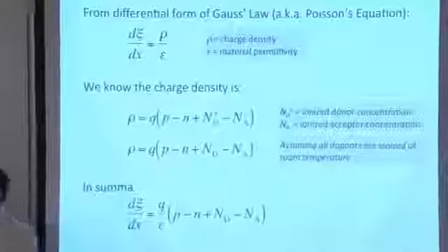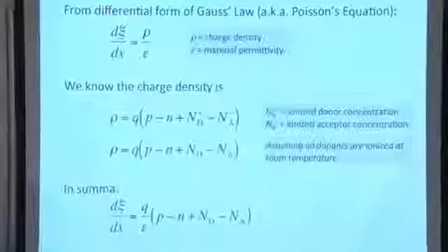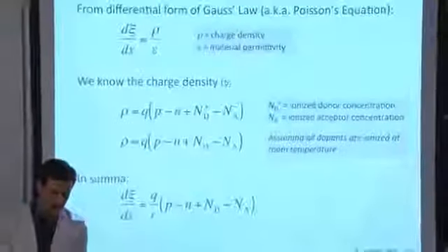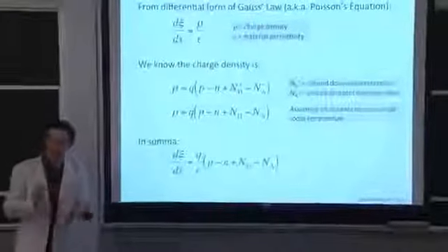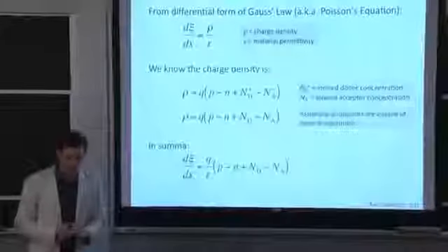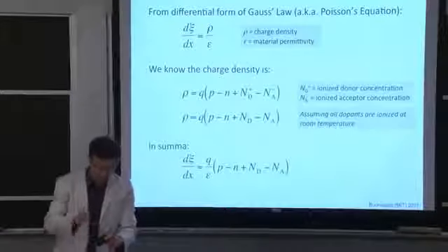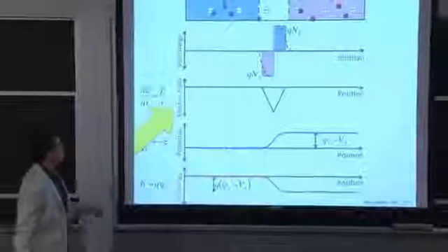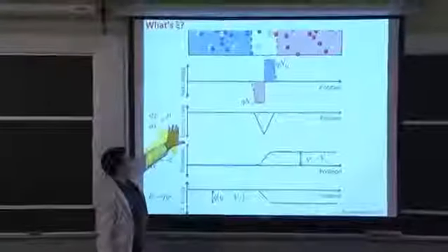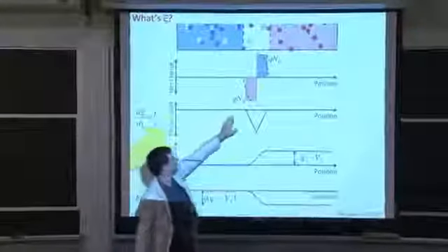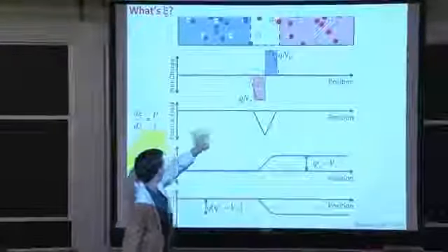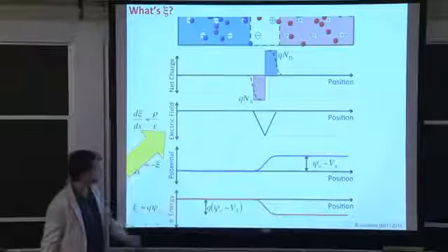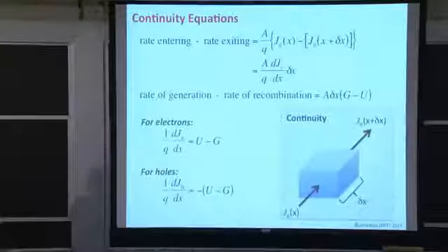We're assuming that everything is ionized, because the binding energy of those free carriers to their dopant atoms is so small that under kT, under thermal energy at room temperature, it's enough to dissociate the charge. OK, so we've gotten to here. Using the box function approximation, we can describe the electric field quantitatively. And now we have to get to the potential and finally electron energy as well.